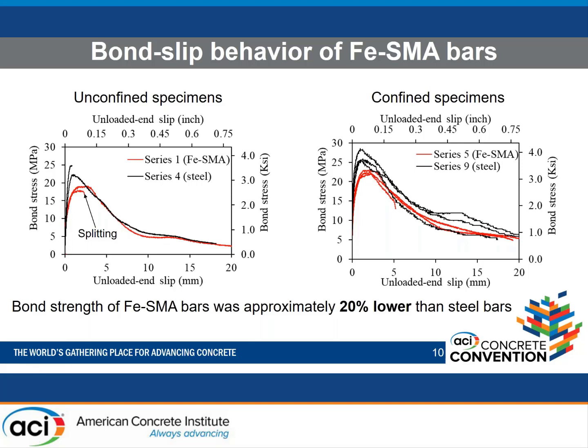The only difference is the maximum bond strength, or the peak bond strength, which was approximately around 20% lower for SMA bars. And if you remember, when I presented the relative rib area for SMA bars, it was smaller than the one for conventional steel bars, and this can be a reason for this difference. But generally speaking, the behavior looks very similar: the ascending portion, the decaying, and the residual at the end.